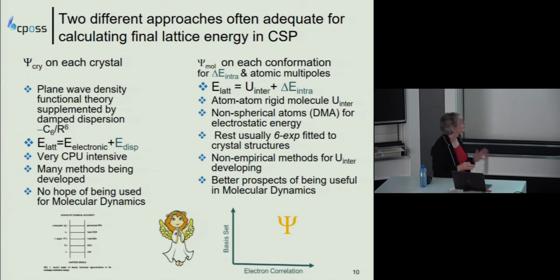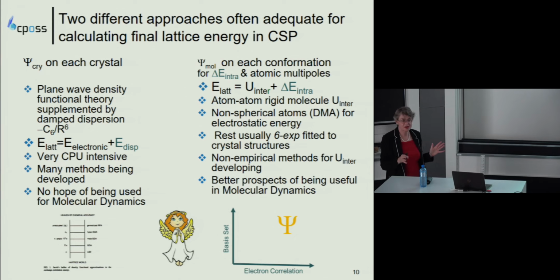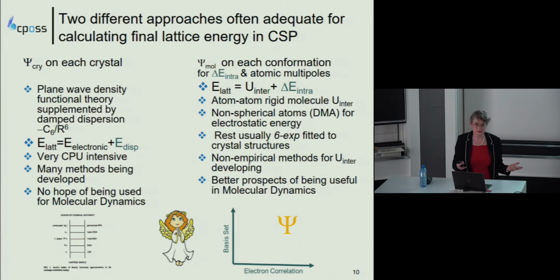So this area has two main strands of how people are calculating the final lattice energy at the end of the process. So one is to do electronic structure calculations on each crystal. Density functional theory has helped, but you'll understand that for these size systems, for this number of crystals, we're still rather on the low level of Jacob's ladder of the quality of functionals. Standard is PBE, and that therefore needs a dispersion correction added on. But there are many methods being developed for this, but there's no hope of using these methods in molecular dynamics.